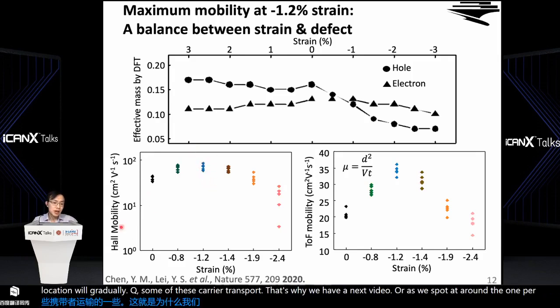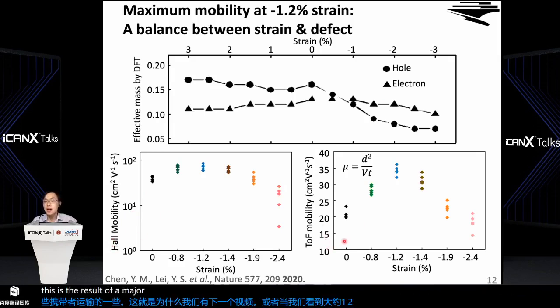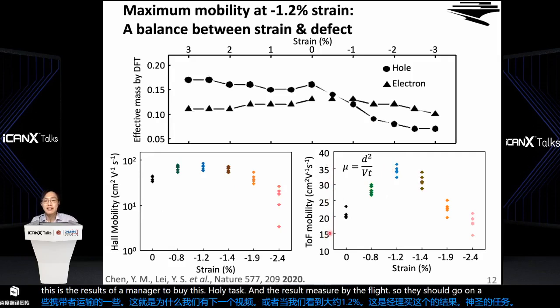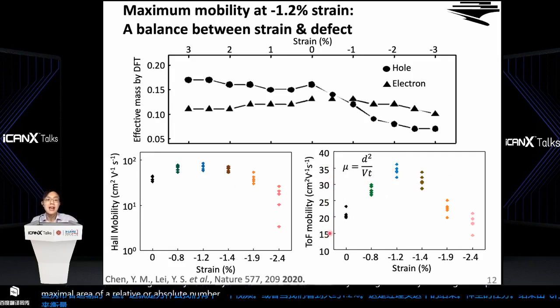So this is the result measured by Hall effect, and this is the result measured by time of flight. They show a similar trend with a maximum value at around 1.2%, but they have different absolute numbers because of the different device structures we use in the experiment and also different measurement setups.